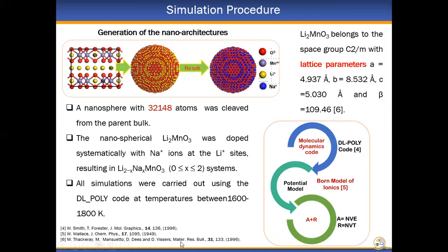We carried out molecular dynamics calculations, which are based on the Born model of ionics. And for all the calculations, the DL_POLY code was used. Amorphization was carried out using the NVE ensemble, and recrystallization was carried out using the NVT ensembles at temperatures between 1600 to 1800 kelvins. Now, in order to generate our models, a nanosphere consisting of 32,148 atoms was cleaved from